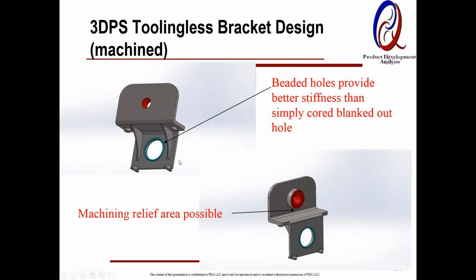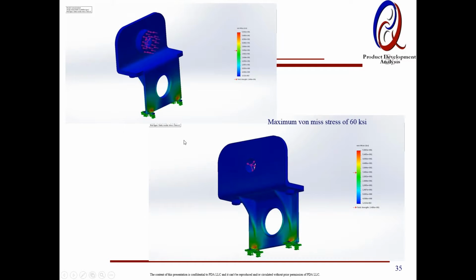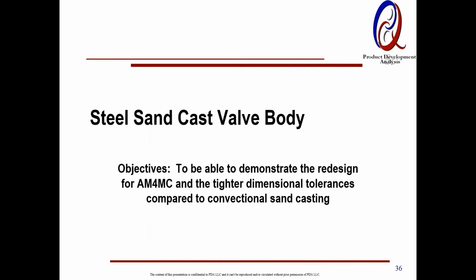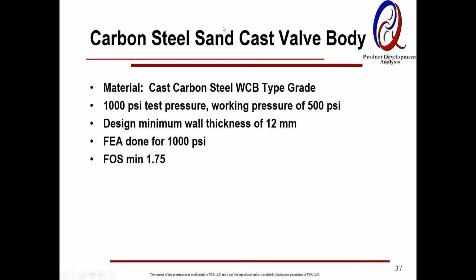In traditional castings, this will create a backdrop. Either you need a loose piece or you need additional cores, and that would impact consistency. So additive, the 3D printed sand, really offers tremendous flexibility and a solution which improves the design. And we were able to incorporate machining relief area and drop the stresses from 72 KSI to 60 KSI.